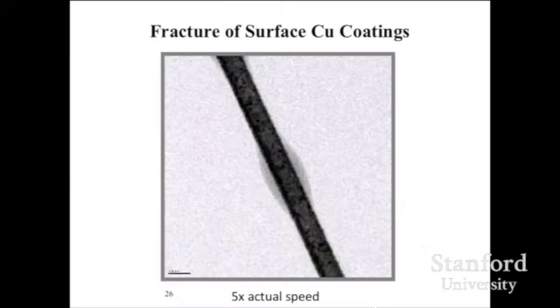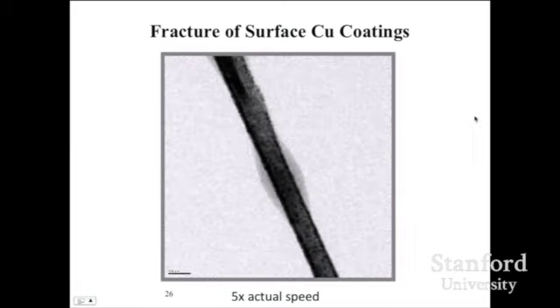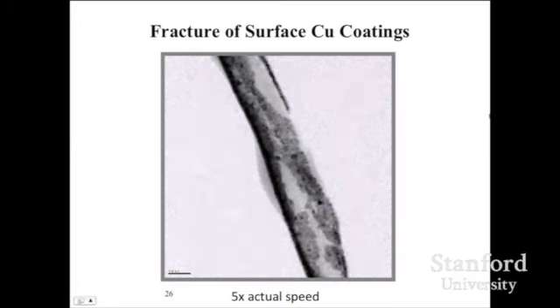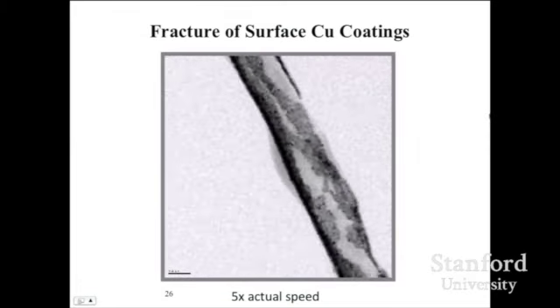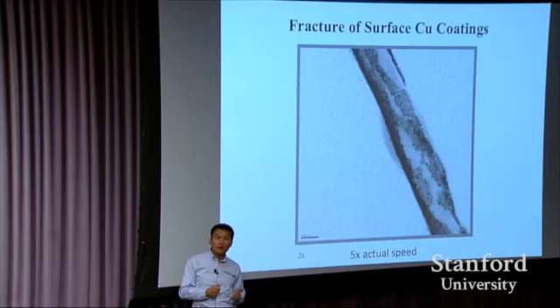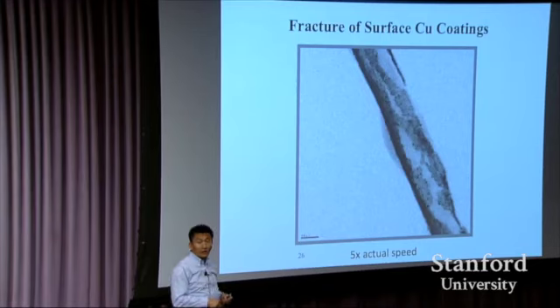Now let's see something dramatic. This is a silicon nanowire, 200 nanometer scale bar, very small, with a copper coating on the surface. Once you start to charge this battery, you see the volume expansion happen in a very dramatic way, and this copper coating is cracking. Nothing can stop this volume expansion. It's just so strong. There's a lot of driving force making this happen. But the nanowire itself does not break.